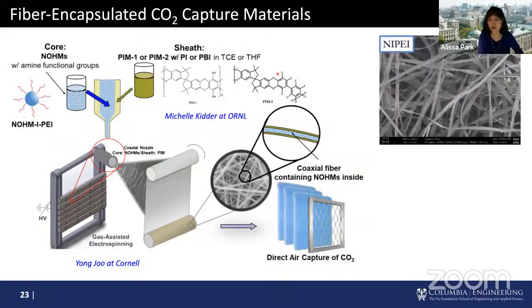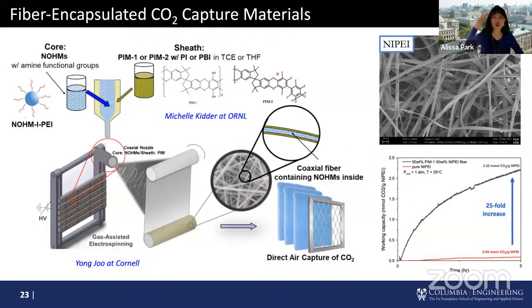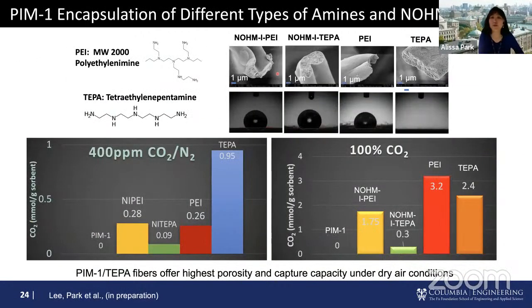And this is the data of CO2 capture. There's a huge boost in CO2 capture capacity. And some of the other NOHM materials we also use, if you look at the top, there are 2 NOHMs on the left and 2 polymer, just electrospun fiber with polymers PEI and TEPA we started with. And by looking at all these, we were able to make fibers. And all of them, especially 3 of them, both NOHM-based electrospun fibers were very hydrophobic. Even PEI-based one was hydrophobic somewhat, but then by the time TEPA, it wasn't hydrophobic.